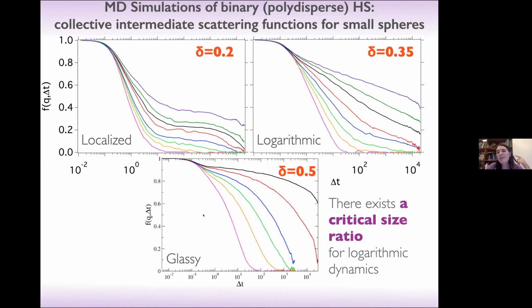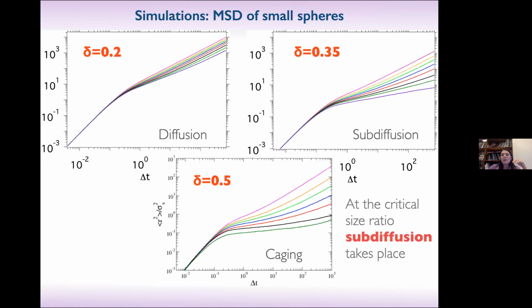And so we further explored the range of possible parameters, and if you increase delta too much, you find that a standard two-step glassy dynamics is recovered, which you see is not continuous anymore. So this indicates that there exists a critical size ratio for logarithmic dynamics. And the same in the mean-square displacement. We saw that it happens in both places.